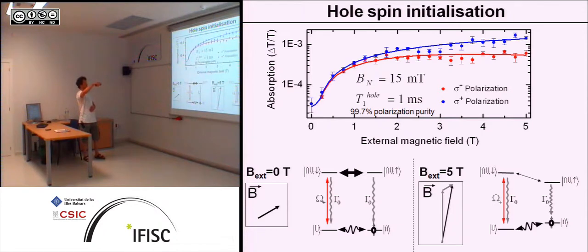So if you look at the absorption contrast, at zero external magnetic field, we get very fast spin initialization, so we pump, and very quickly we are here, and then the system can't excite anymore. But for example, at 5 Tesla, we have very slow coupling, and we will only very, very rarely end up here. So that means most of the time we have just a normal transition here, and that's why we see strong interaction. So here you see the strength of the absorption signal. At 0 Tesla, it's very effective spin pumping. So effective spin pumping means no interaction, and then we have small absorption contrast. And then the absorption signal comes back slowly while we increase the external magnetic field.